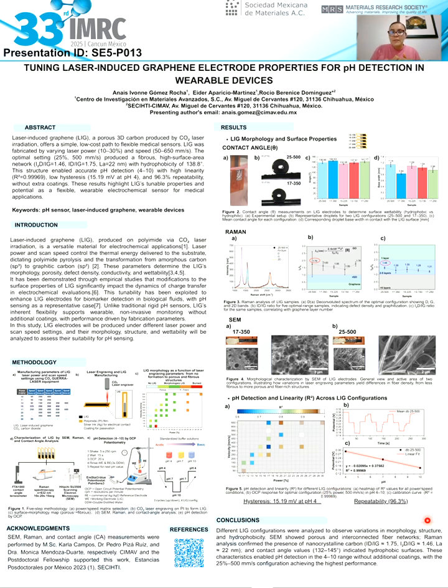The average repeatability was 96.3%, meaning the sensor maintained almost the same potential value at the same pH in repeated measurements, even without additional coating. Hysteresis was calculated as the potential difference for pH 4 between the beginning and the end of the measurement cycle. This value shows whether the sensor response shifts after several pH changes.